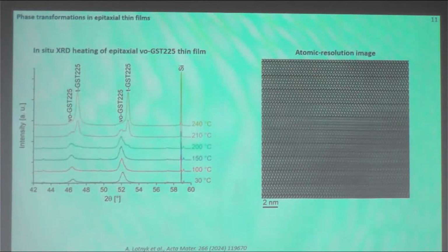The transformation from the vacancy ordered phase, for example to the trigonal phase, can also be studied by in situ X-ray diffraction. In situ X-ray diffraction, I think, is a well-known method, also available here. It needs a filter, but in this case we also use a heating stage to heat up our system containing vacancy layers. This is an epitaxial thin film, and if we start to heat it up, we can go through different phase transitions.